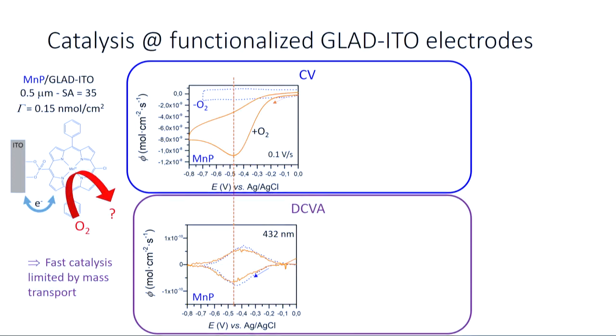What is maybe more interesting is to look at what's happening now under turnover conditions. In this specific case, we analyzed the reactivity of this chromophore toward dioxygen reduction. Porphyrins are widely used for their catalytic activity toward dioxygen reduction, CO2 reduction, and so on. So in that case, from cyclic voltammetry, you have the catalytic current. And you can see here that you have a huge enhancement of the current intensity, and at some point you have a peak here, meaning that you start to be limited by mass transfer of the substrate that has to reach the electrode.